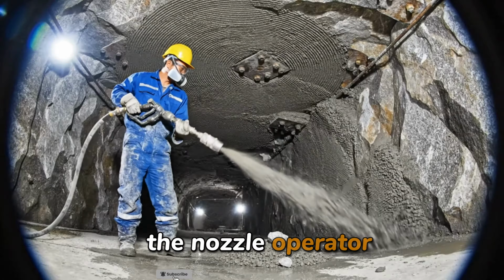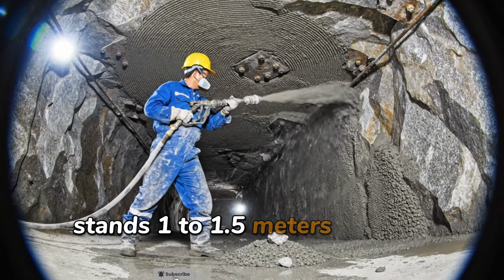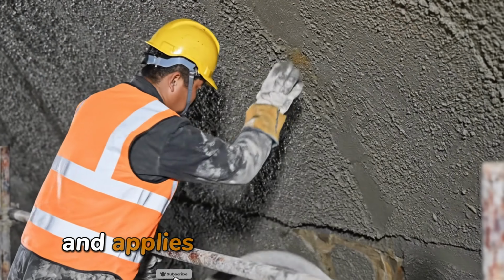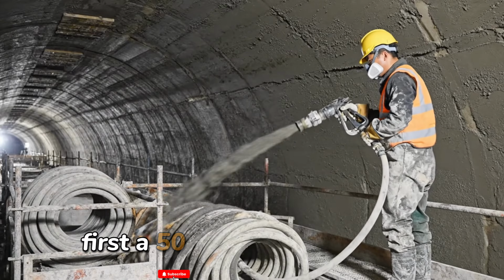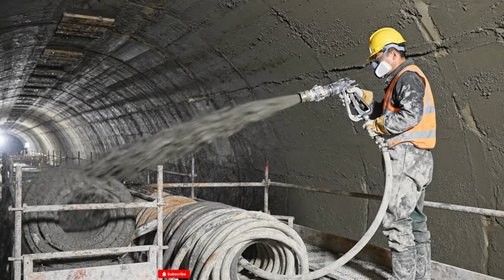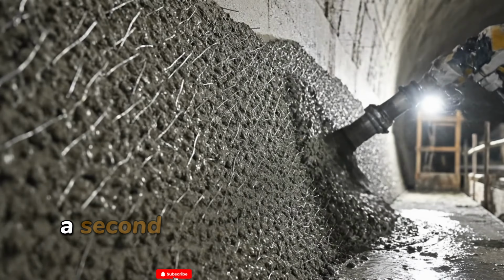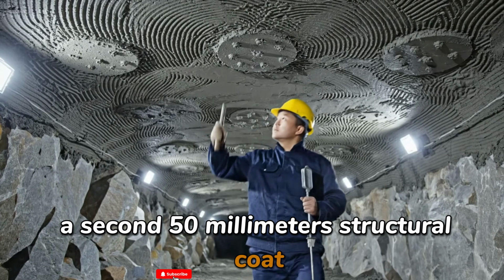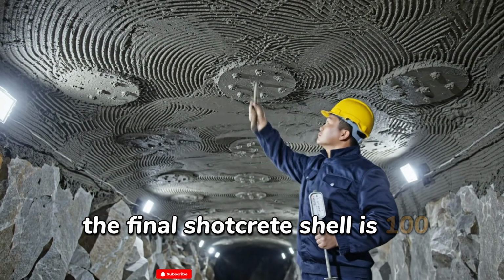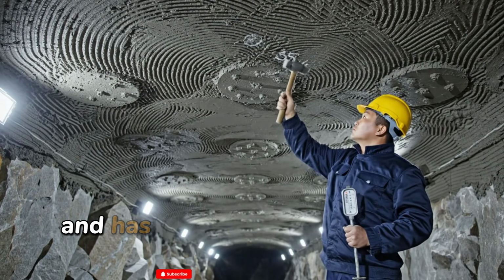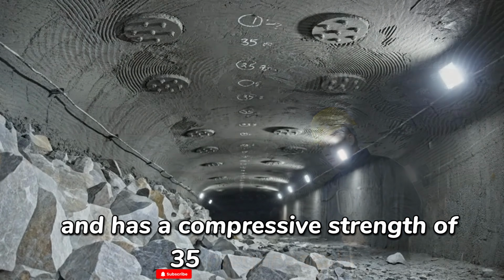The nozzle operator stands 1 to 1.5 meters from the surface and applies the shotcrete in layers, first a 50 millimeters base coat. Then, after it cures, a second 50 millimeters structural coat. The final shotcrete shell is 100 millimeters thick and has a compressive strength of 35 megapascals.